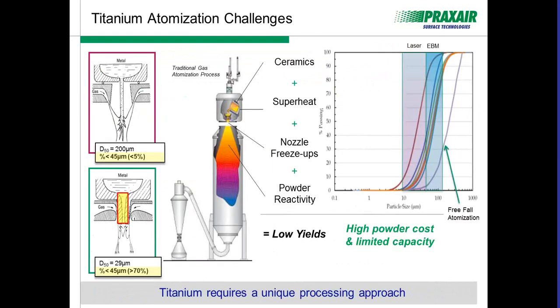We're going to switch gears a little bit to our newest production cell and our newest technology, and that's titanium atomization. Titanium atomization offers many challenges, and there are ceramic challenges, meaning that as you melt titanium, you can't use traditional refractory crucibles. It eats into that crucible. It can actually break out of that crucible, and it contaminates the liquid very quickly. So you use a special crucible, and that's a water-cooled copper crucible. This would be a water-cooled copper crucible example.